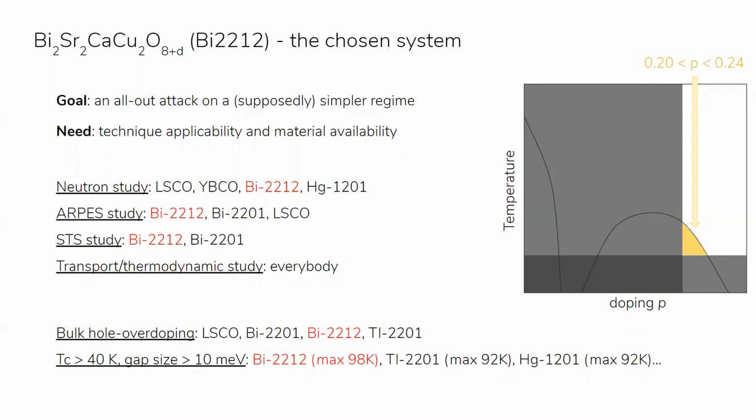Let me ask you, in the overdoped regime, is this supposed to be homogeneous or inhomogeneous? I thought there was some earlier claim saying the overdoped regime actually has puddles, right? Pengcheng, I think you already asked one of the questions from the later slides. To put it short, when we talk about homogeneity, it always has a length scale attached to it. STM has already observed nanometer scale inhomogeneous electronic density of states locally in the overdoped system. In particular, this is not specific to overdoped cuprates. It's persistent for all dopings.